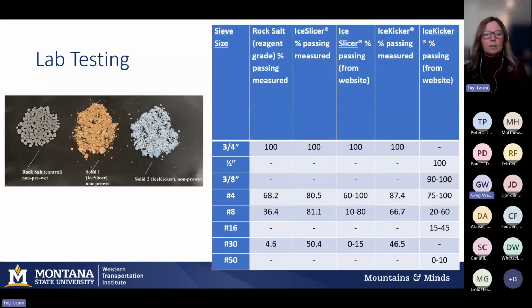So one interesting piece of this with the solid products is we did a gradation analysis. Here you can see a picture of what these products look like. On the left-hand side, we have the purchased or lab grade, reagent grade rock salt. We have Ice Slicer in the middle, and we have Ice Kicker. Initially we pulled the gradation analysis provided by the vendors because we were going to use those products as is. We weren't modifying them. But we did want to tailor the gradation of the reagent grade salt to be as close or within range of the commercially available products. What you can see here on this table is the different sieves that were used in the gradation analysis and what was measured.